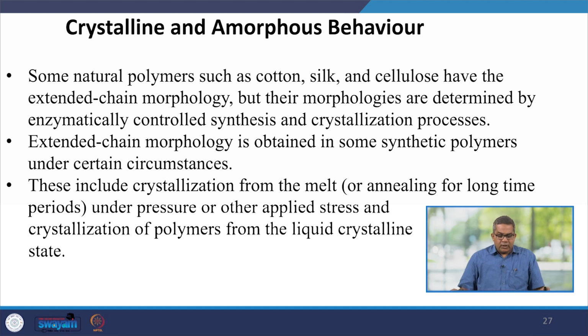Some natural polymers like cotton, silk, and cellulose have the extended chain morphology, but their morphologies are determined by enzymatically controlled synthesis and crystallization processes. The extended chain morphology is obtained in some synthetic polymers under certain circumstances. This includes crystallization from the melt under pressure or applied stress, and crystallization of the polymer from the liquid